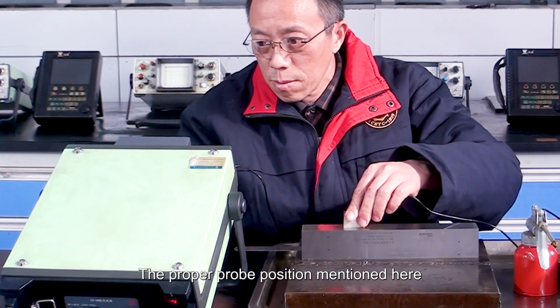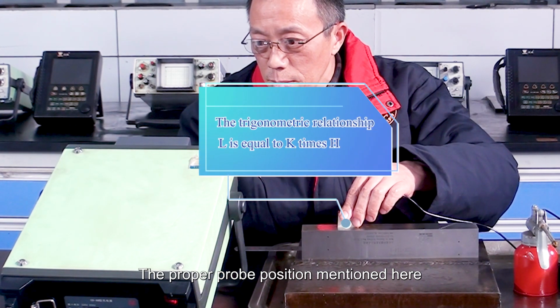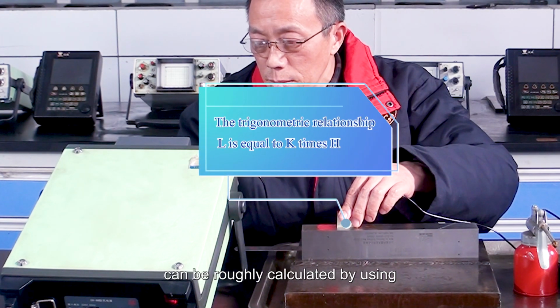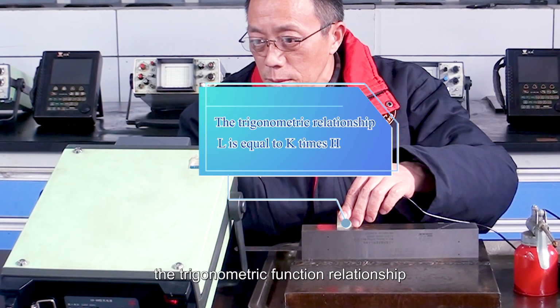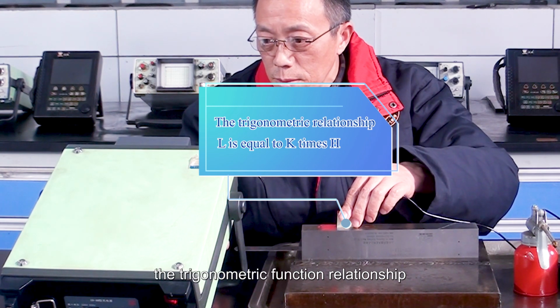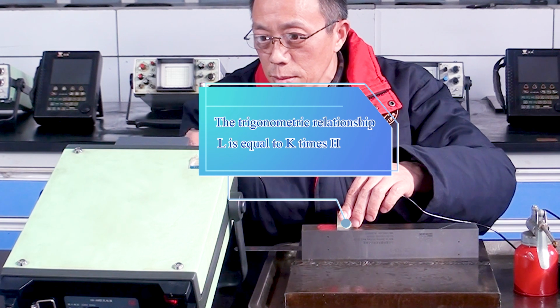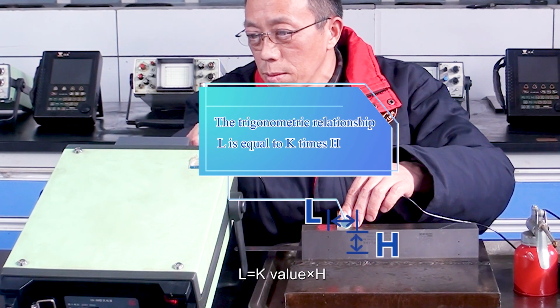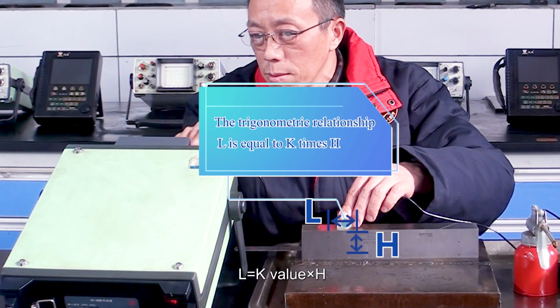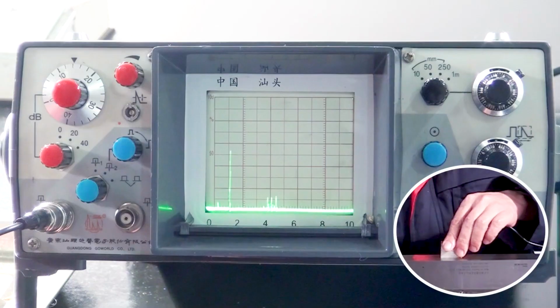The proper probe position mentioned here can be roughly calculated by using the trigonometric function relationship L equals K value multiplied by H.